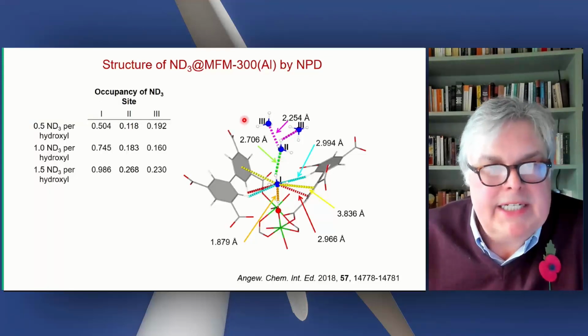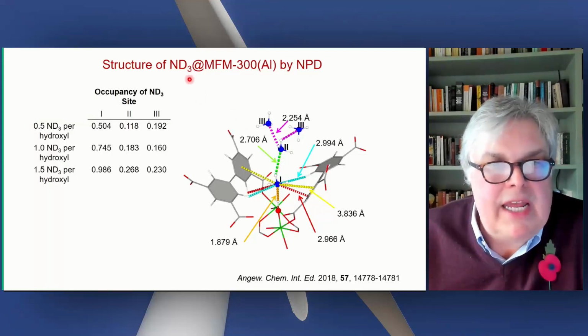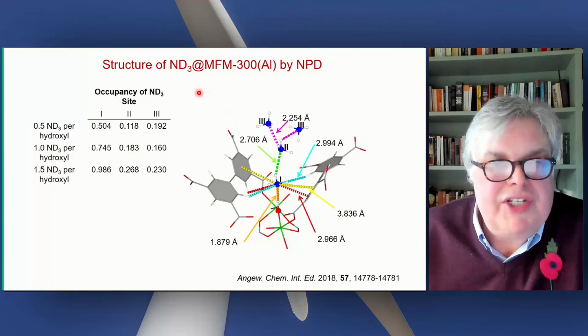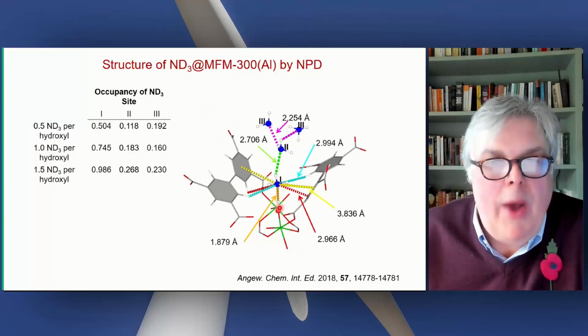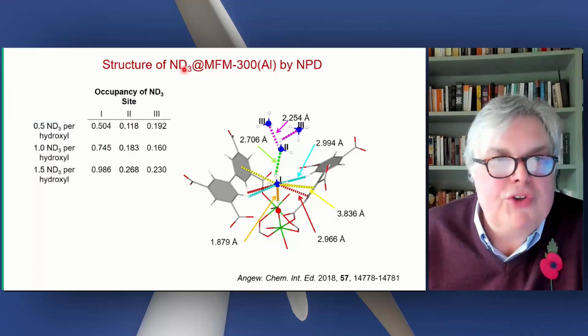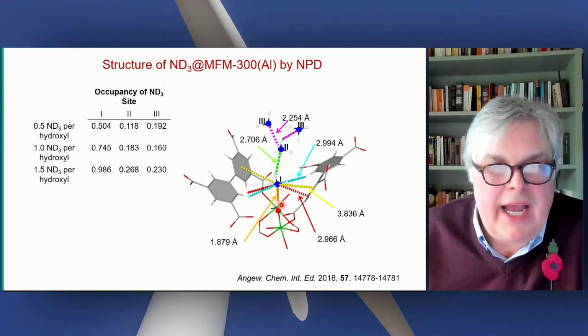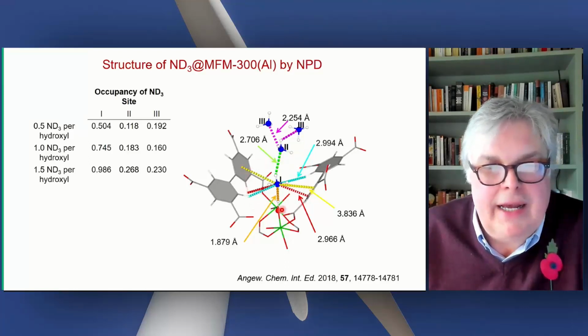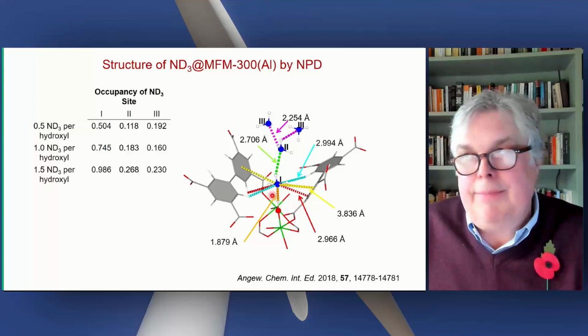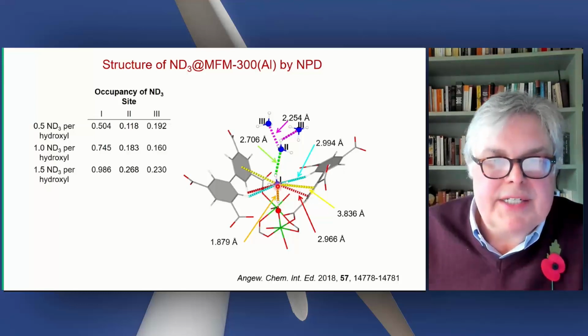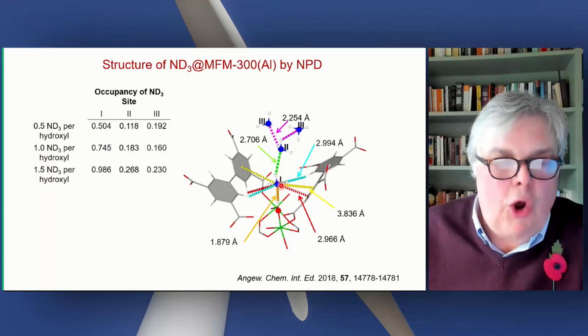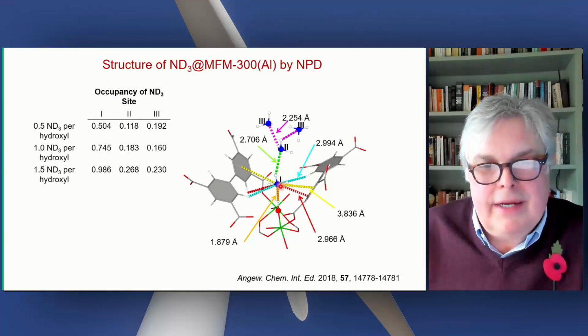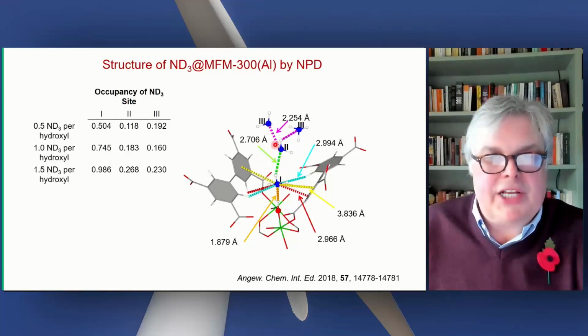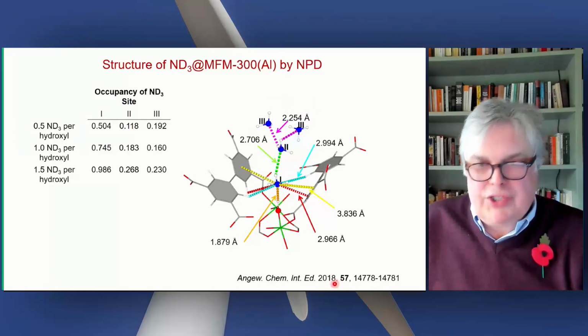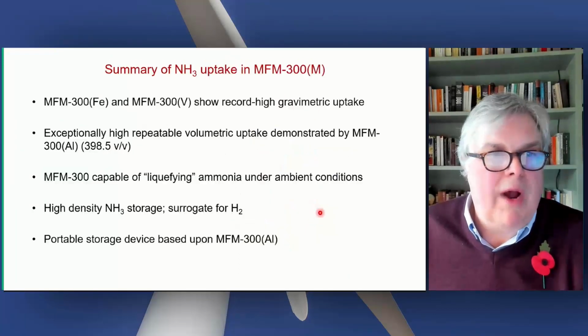This was complicated because if you introduce ND3 into your MOF, there's a deuterium-hydrogen exchange between the OH group here and the deuterium on the nitrogen. So this site is a mixture of H and D, and you end up with HD scattering or HD mixing on the nitrogen center. So exchange between those sites complicates the structural analysis. But essentially, you see ammonia-ammonia interactions within that pore as well.